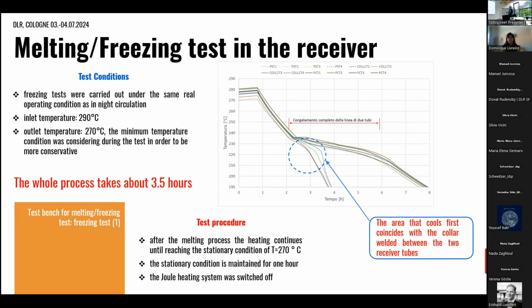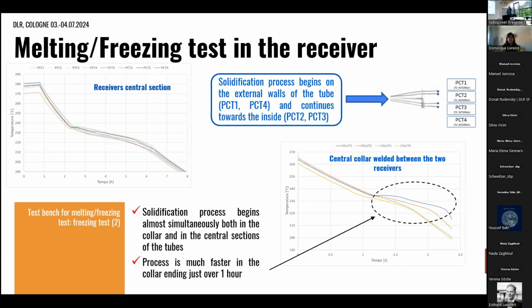Here we can see that the area that cools first coincides also in this case with the weld between the two receivers, and the whole time necessary to complete the process is about 3.5 hours. So it's faster than the melting process. In detail, we can see that